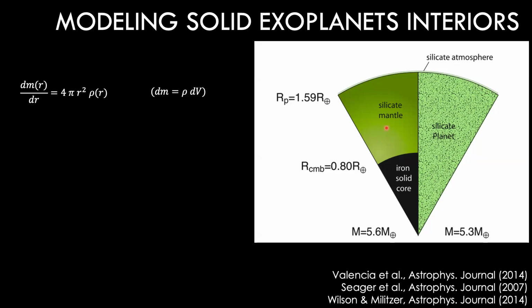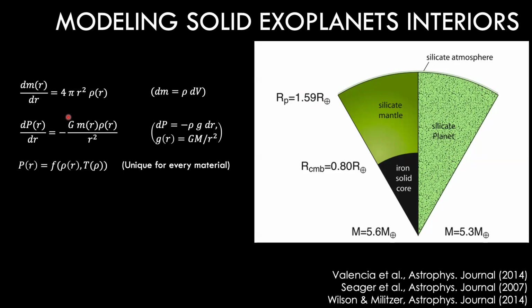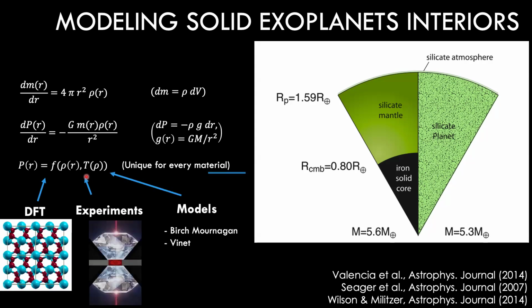And you have to solve a few equations, like an equation for the mass, which is literally the mass enclosed in a spherical shell of density rho. And you have to balance the pressure with the gravity, basically to prevent your planet from imploding, and an equation of state. The equation of state is the relationship between pressure, density, and temperature that is unique for every material. So every material that you put in your model needs to have this characterization. And where do you have this from? From experiments or the simulations that I perform. So once you have all these three equations, you solve them. It's a set of three coupled differential equations.